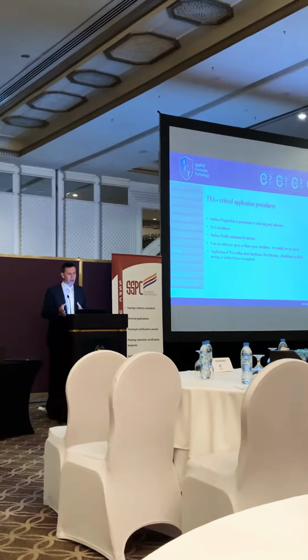The other critical thing about TSA is the time frame between blasting and application. It's always important, even in liquid coatings, but in TSA it's even more important. You can't have any flash rusting. The surface has to be absolutely clean. So 4 hours is a maximum. And even on high humidity days, you might find that 4 hours is too much. So that is a critical element of the TSA process.